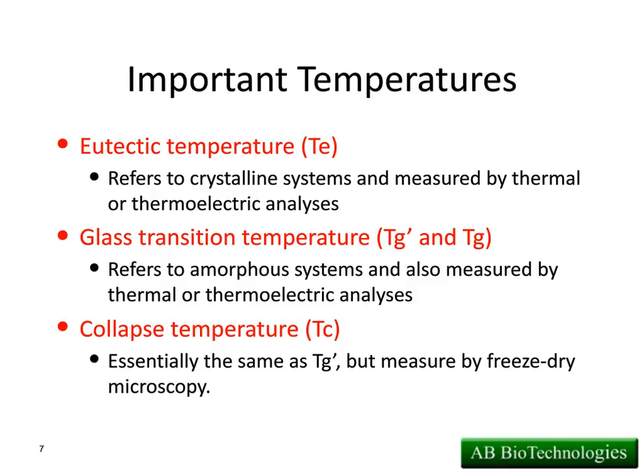Now, this becomes extremely important because in primary drying, the goal of primary drying is to remove the ice in the ice channels. Okay. Now, ice acts as scaffolding in the frozen product. So say, for example, we freeze the product, ice is solid in the ice channels, but we're slightly above our glass transition temperature. So the ice is solid, it looks frozen, but in the interstitial space, it is still a fluid. You can't see this with a naked eye. It looks frozen. However, if we start primary drying and we start pulling the ice out of the ice channels, and that interstitial space is not a solid, this is where we get collapse. And I've got an image of a vial here, I'll show you in a couple slides, but this is where you open up your freeze dryer and all your vials are full of a little puddle of goo. We don't want that.